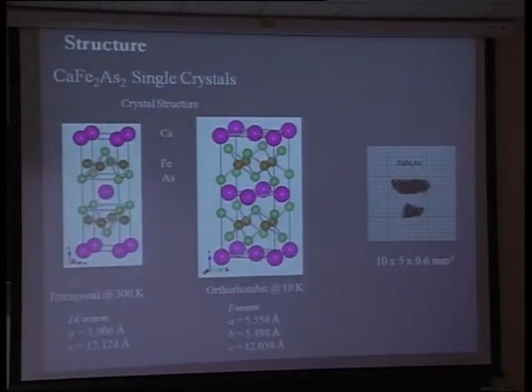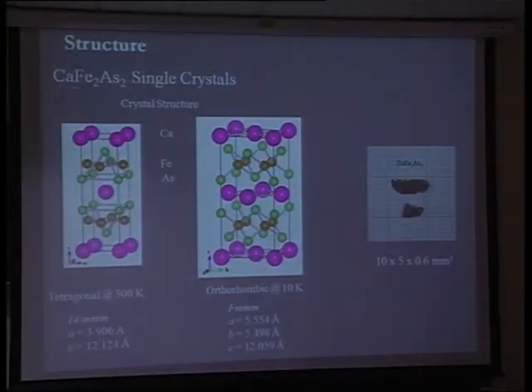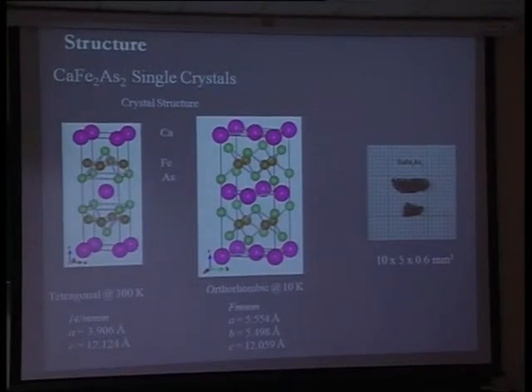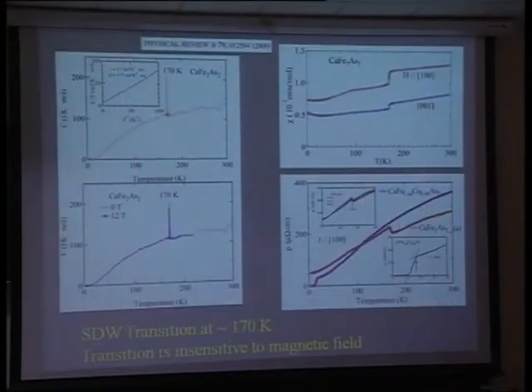So this calcium iron two arsenic two, which is in this iron-based superconductor family, 1-2-2, the structure is like this. You can put calcium, strontium, barium here, it doesn't matter, the structure is very similar. At room temperature, they are tetragonal, and if you go to low temperature, there is a transition to orthorhombic phase, and at the same time, there is a magnetic transition. So it becomes a spin density wave kind of phase at lower temperature. Okay. So this actually is very robust.